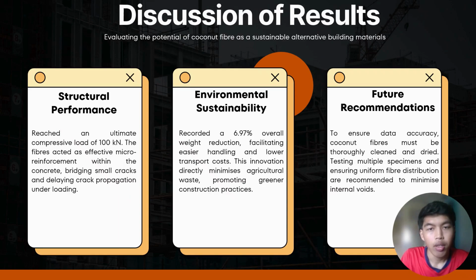The study evaluated the incorporation of 5% coconut fiber into hollow concrete brick. These results show a weight reduction of approximately 7% after a 7-day curing period. This reduction resulted from water evaporation and the naturally lower density of the coconut fibers. Despite its lighter weight, the brick successfully achieved an ultimate compressive load of 100 kilonewton.